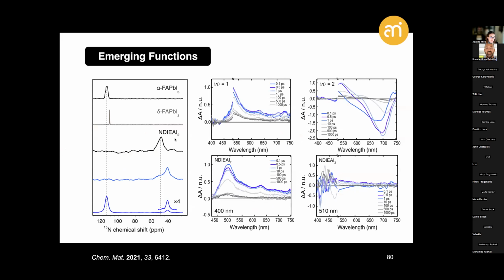by NMR the presence of these systems, stabilizing also the desired alpha phase, but importantly, showing the direct electronic exchange between the inorganic and the organic phase that is illustrated here by transient absorption spectroscopy, in particular by looking into different two-dimensional perovskite architectures, revealing the presence of this absorption between around 550 and 600 nanometers that directly corresponds to the formation of the NDI radical anion, as illustrated here in the meta spacer upon excitation at 400 nanometers that